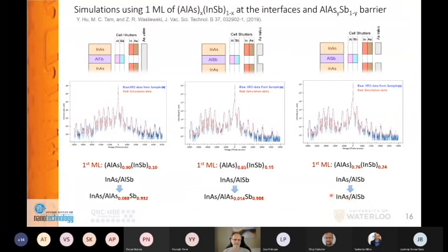However, when we move to a fully closed valve, then we can indeed grow a pure aluminum antimonide. And we still have a substantial amount of arsenic at the interface, giving predominantly aluminum arsenide bonds, but already at only 76%. And so that really supports the idea that the aluminum arsenic bond is stronger than indium antimonide, and it very likely is the reason behind it. But for sure, the presence of residual arsenic in the chamber is also playing a very important role.